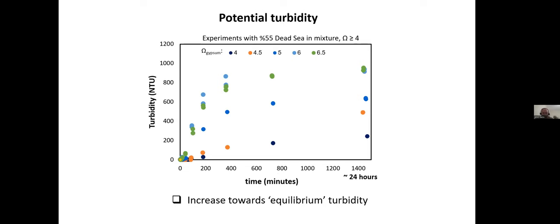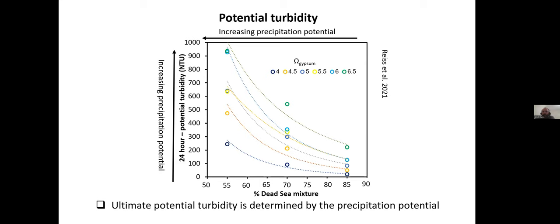Now, if you look at the potential turbidity, so over time, it kind of levels off. This is because the experiments get closer to equilibrium, gypsum starts precipitating, so we reach some maximum value. So we could just look to what happens at the maximum value, or when we obtain the potential, when we basically got to the maximum potential of precipitation, the most gypsum that will precipitate. And we basically see that there's a relationship between the measured turbidity, which is the y-axis, and the precipitate. And this is fine because we know how to calculate the potential precipitation. We know how much would precipitate, so this correlation is nice.